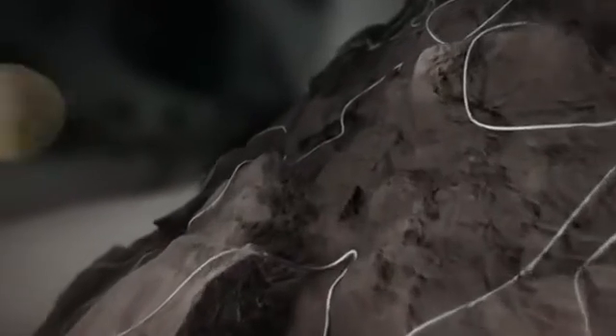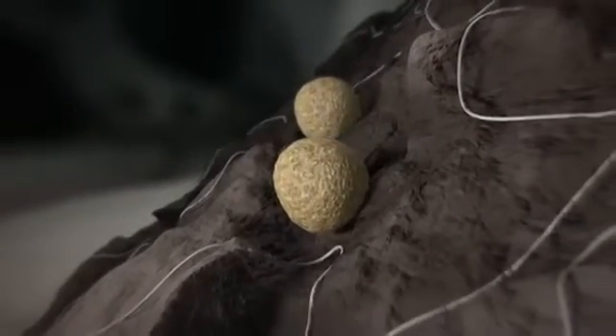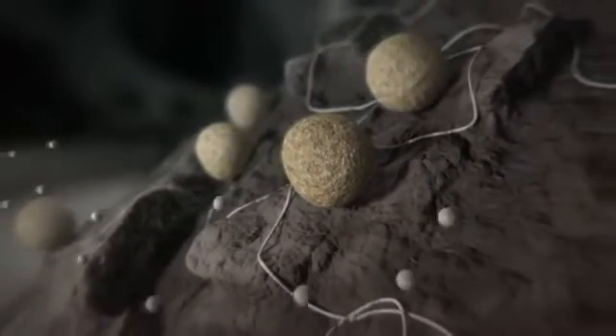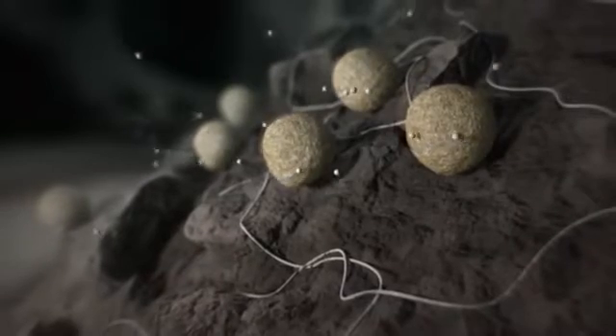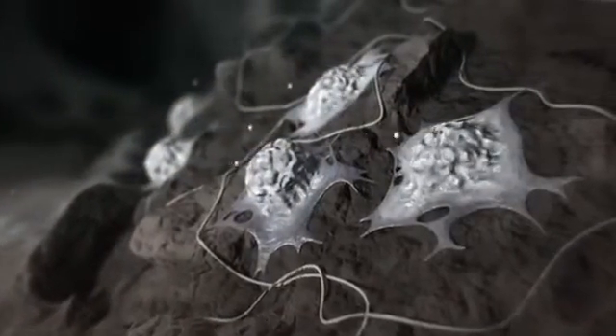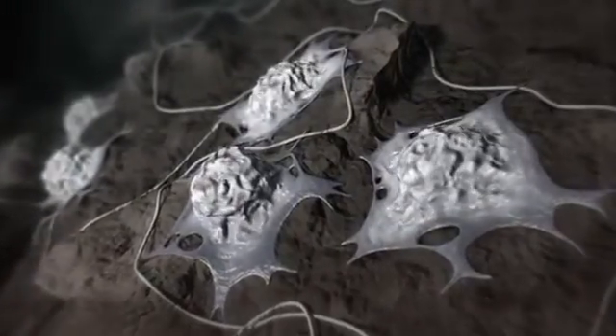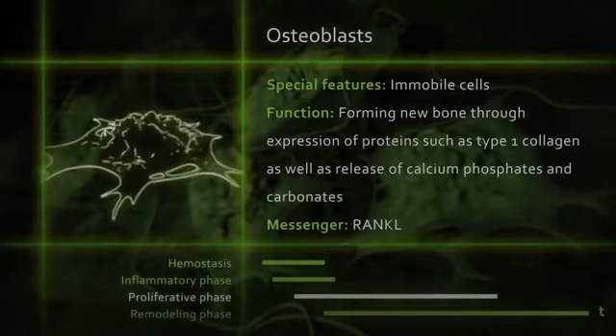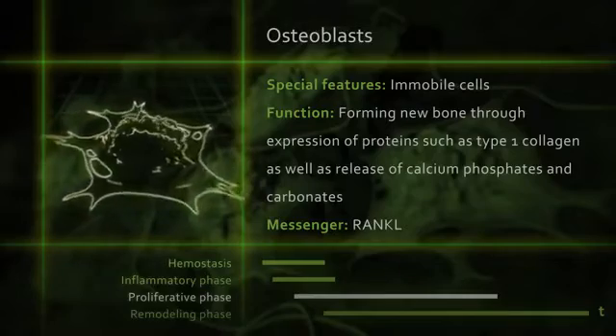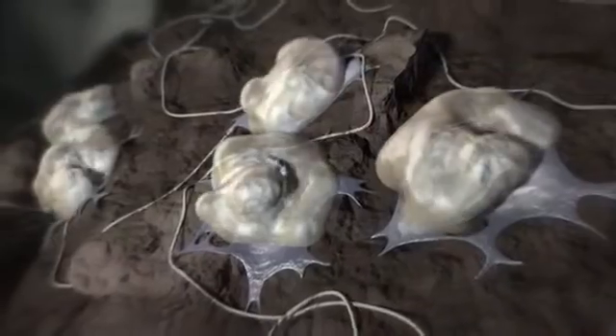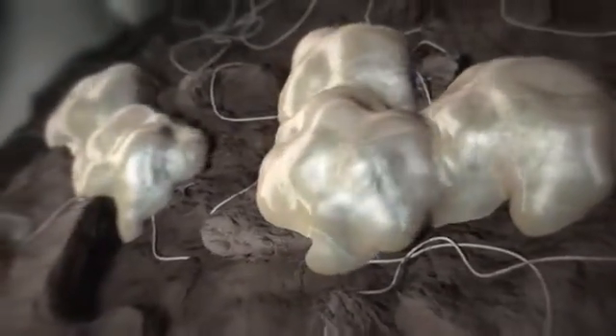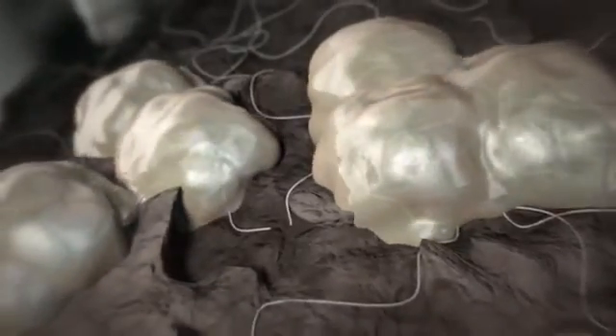Perivascular cells not only create new blood vessels — they also migrate toward existing trabeculae and to the implant surface, where they differentiate into new osteoblasts under the influence of BMPs from the dissolved bone. The adsorbed proteins such as fibronectin have a crucial influence on the attachment of bone progenitor cells to the implant surface. The osteoblasts form an organic matrix that is mineralized by incorporating calcium phosphate. Under the optical microscope, bone is visible on the implant surface; under the electron microscope, a thin protein layer is seen between the bone and the titanium surface. Mechanical stability is ensured by interlocking with the surface of the implant.